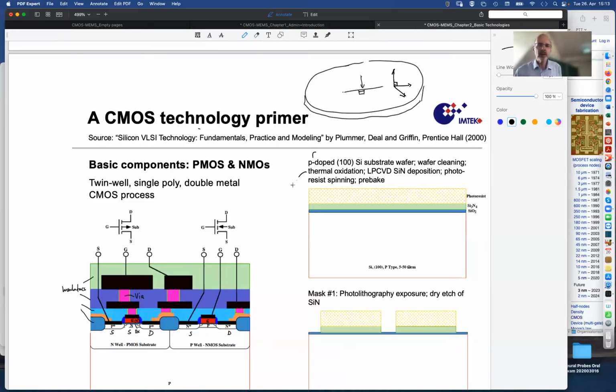This produces this little bluish oxide layer, a thin layer, which is also called the pad oxide, or stress relief oxide, by the technologists, because it is actually only a glue to the next layer that is elaborated on top, namely the silicon nitride. SiN means silicon nitride, and it is here explicited as a stoichiometric Si3N4. But it's an amorphous layer. It's not a crystalline layer.